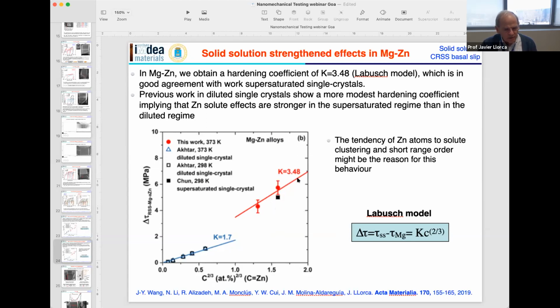We can see here also that the Labusch model is also applicable for the case of magnesium-zinc alloys, but the slope, the coefficient of the Labusch model, when you have high zinc content is different than when you have low zinc content. Basically this can be explained because of the tendency of zinc atoms toward solute clustering and short-range order that may increase the strengthening effect.